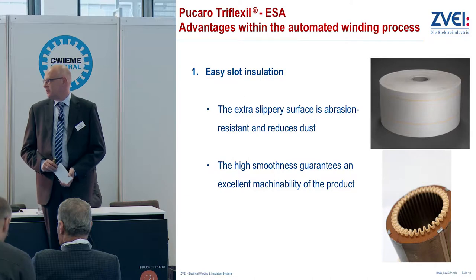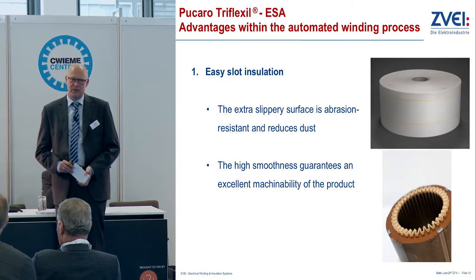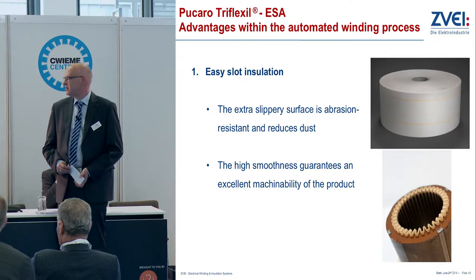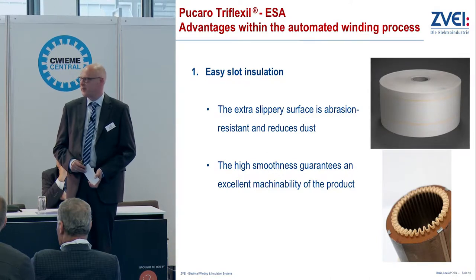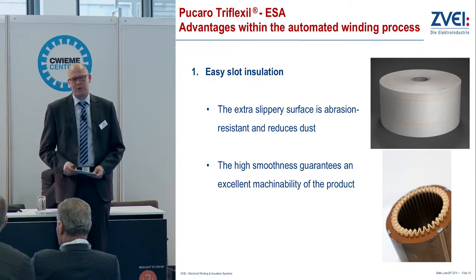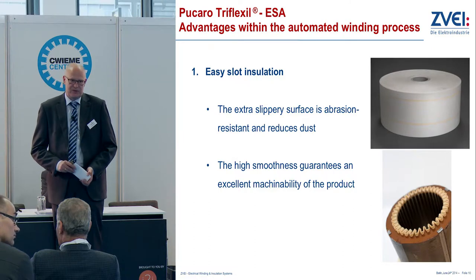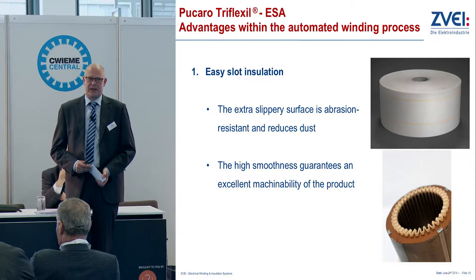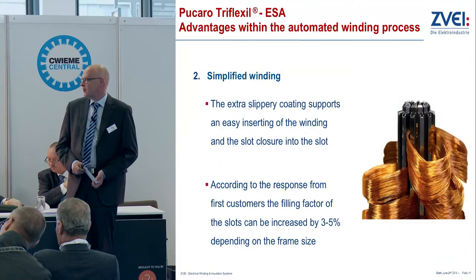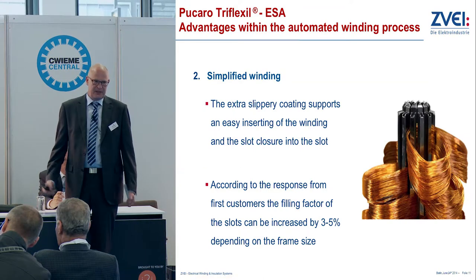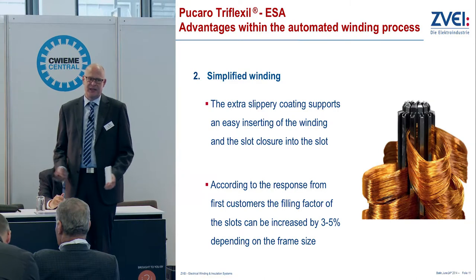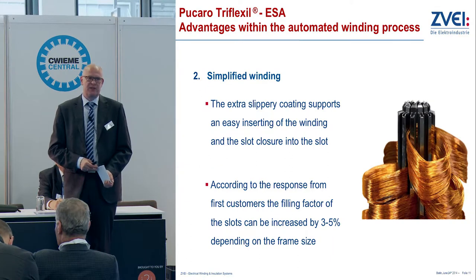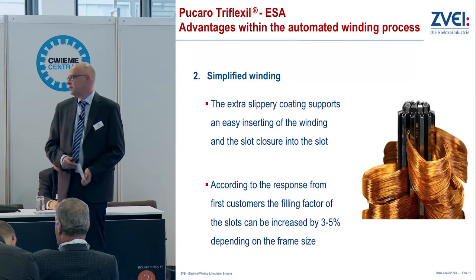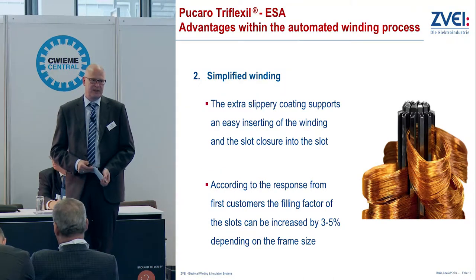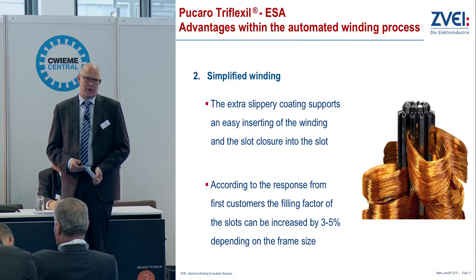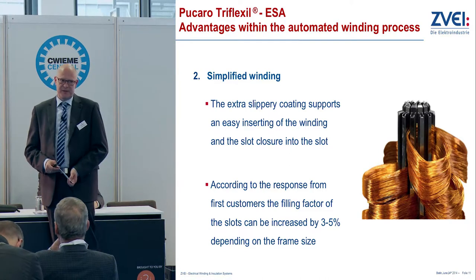The properties we achieved with a very thin top coat, approximately 2 to 5 microns, are that we even improve the abrasion resistance of the Nomex material. And this top coat guarantees a high smoothness. That was the goal of the development, and so we have a better machinability of our product. Especially when we are using automatic machines where the winding is made outside of the stator and then inserted together with the slot closure, this is a very smooth process due to the new material. And according to our first key customers who are using this material, they are able to increase the filling factor by approximately 3 to 5%, depending on the frame size of the electrical motor.